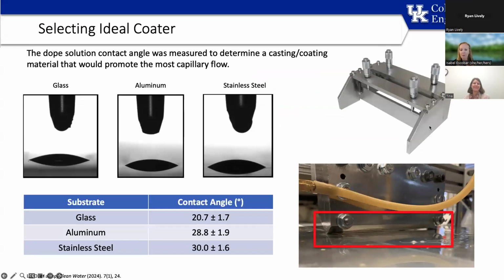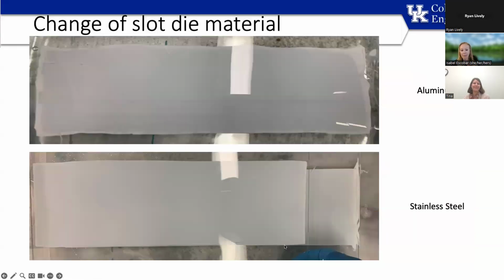Another issue that we have when we're dealing with a doctor blade, we're dealing with a stainless steel doctor blade. It is what it is. With a slot die coater, we can have glass, aluminum, or stainless steel for the coater itself, and all of those provide different contact angles with the polymer, with the dope solution. So those also impact how well that dope comes out through the slot die and makes a membrane. And here we have a membrane made with an aluminum versus a membrane made with stainless steel.